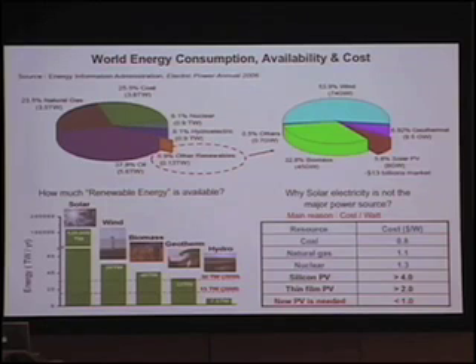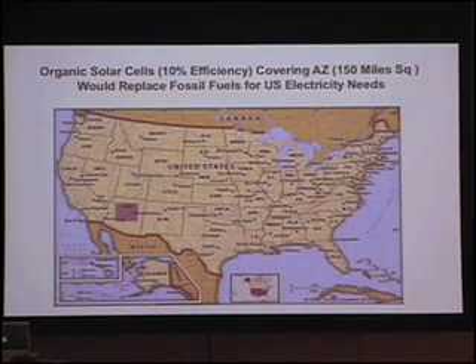If you look at a lot of European countries that utilize solar cells, they are heavily subsidized by the government. So if we really want a sustainable, deployable technology, you really need to develop photovoltaic cells below $1 per watt. People did a very brief calculation of how much solar cell coverage we need to generate enough energy for the United States. This shows that if we can have polymer solar cells with 10% efficiency and cover Arizona with about 150 square miles of area, you can generate enough electricity to power the whole United States.